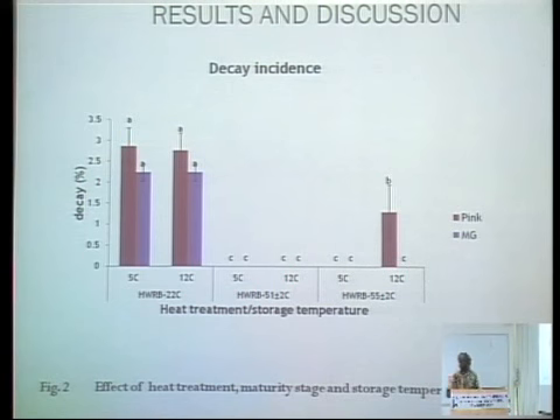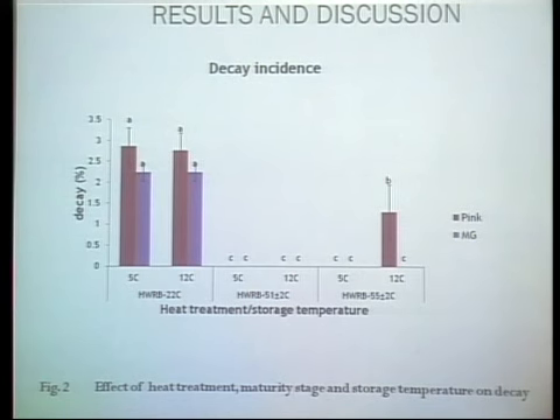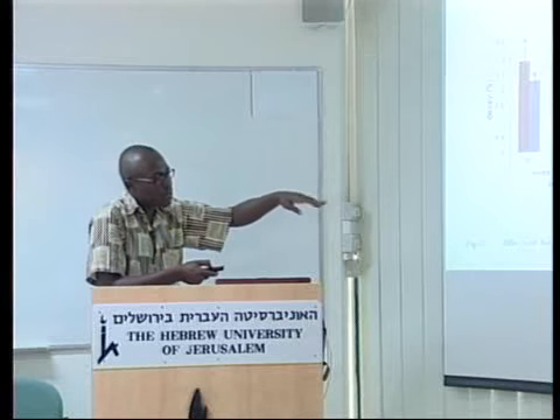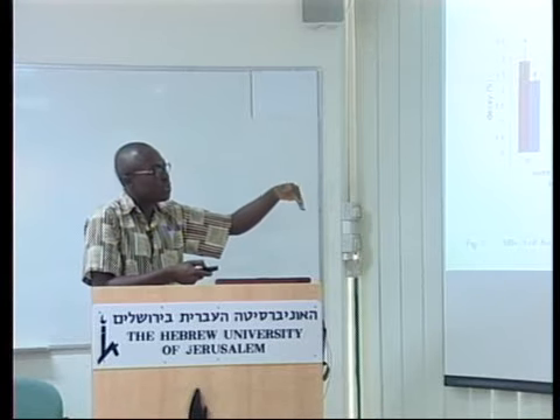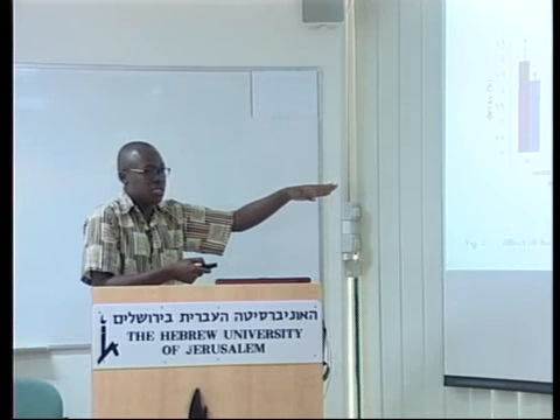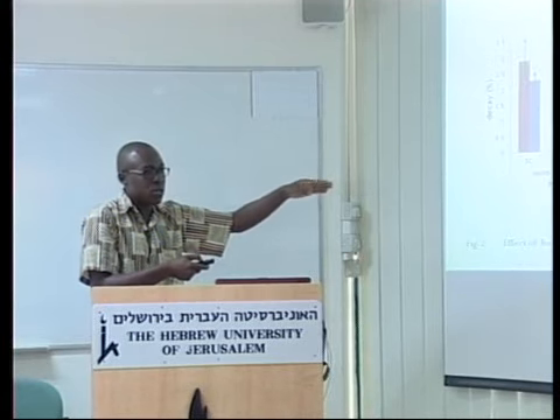So the idea, we washed this fruit at 51 and at 55. But in my materials and methods, I mentioned that Fallik et al. also did a similar experiment, but it wasn't at 51. It was at 52. So 51 plus or minus 2 will be able to inhibit decay and chilling injury. But at 55 or above, of course, it can inhibit chilling injury, but it can cause decay due to heat damage.